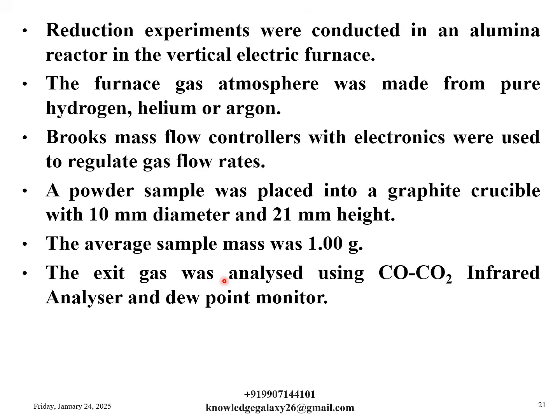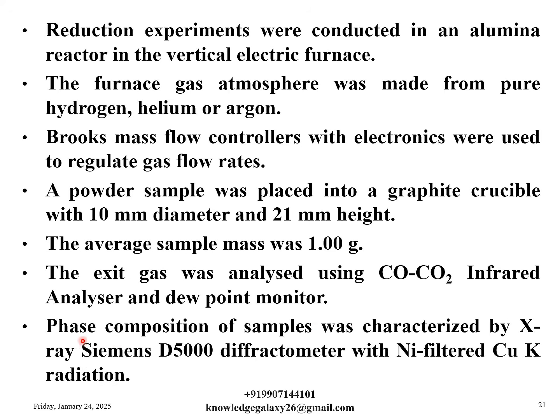The exit gas was analyzed using CO-CO2 infrared analyzer and dew point monitor. Phase composition of samples was characterized by X-ray Siemens D5000 diffractometer with nickel filtered copper K radiation. Copper K means copper K-alpha radiation.